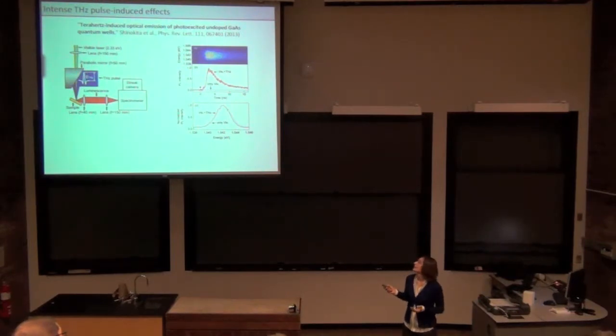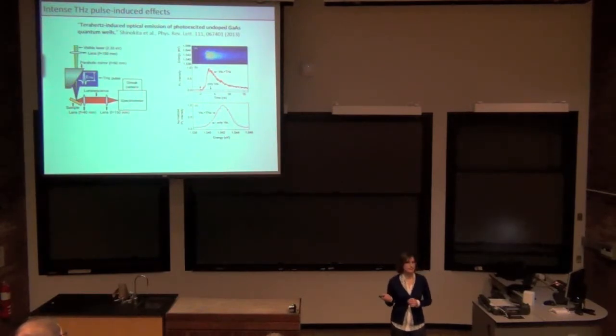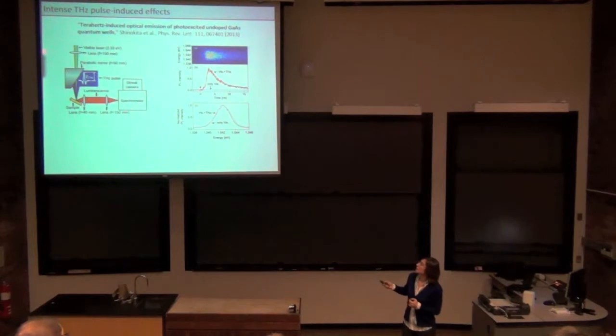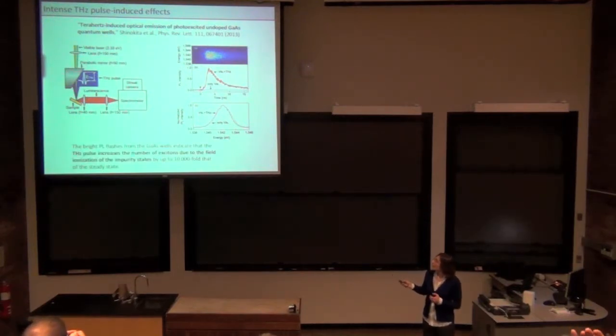Great. But then when they come in with a terahertz pulse, what they see is a huge increase in intensity. They chopped this pulse to make it into 15 nanosecond pulses, and when they timed it to their terahertz pulse, what they see is a 10,000-fold increase in intensity.